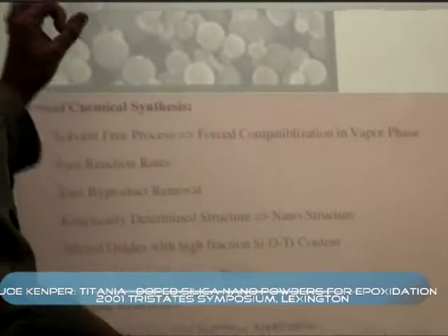The rate of the reaction to make the catalyst is severely enhanced when it occurs in sub-micron size aerosol droplets, over what happens in a beaker, partially by byproduct removal, which is rapid in small droplets due to enhanced vapor pressure in these droplets.